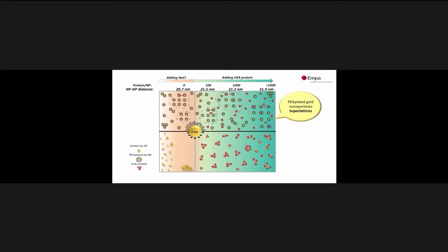Whereas an already small amount of protein helps to stabilize the citrate-stabilized gold particle suspension. In a later stage, we might see a hybrid formation between particle and protein in a not well-defined structure. Sometimes we see particles very close to each other, sometimes not. So here we probably have an arbitrary distribution of hybrid systems of protein and particle.